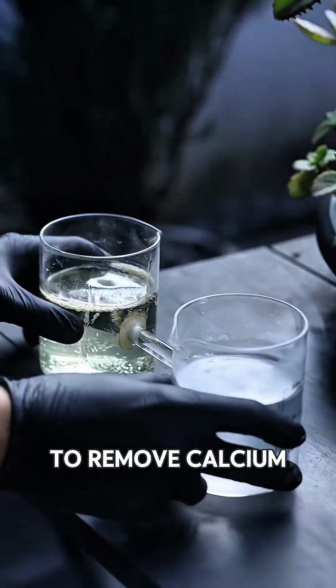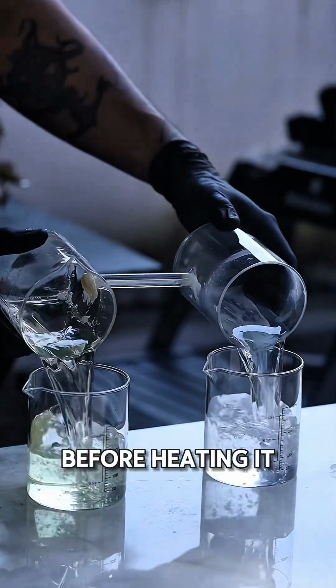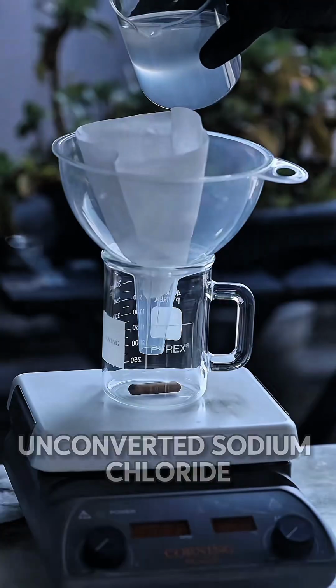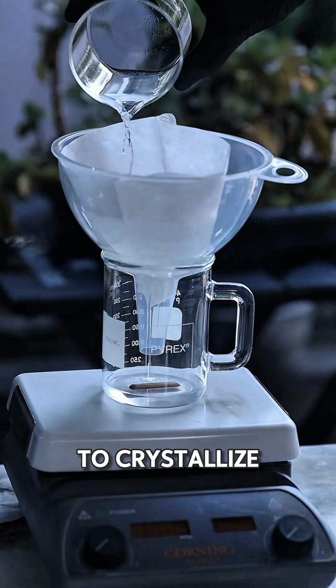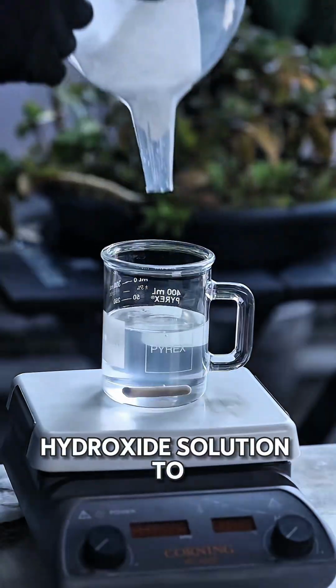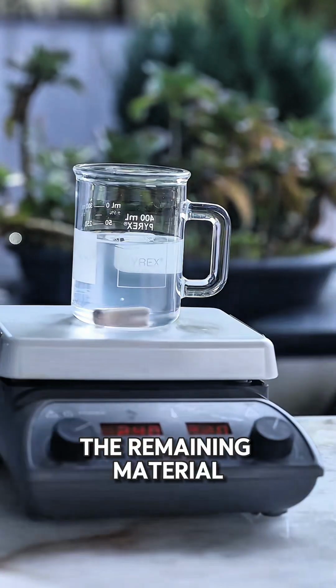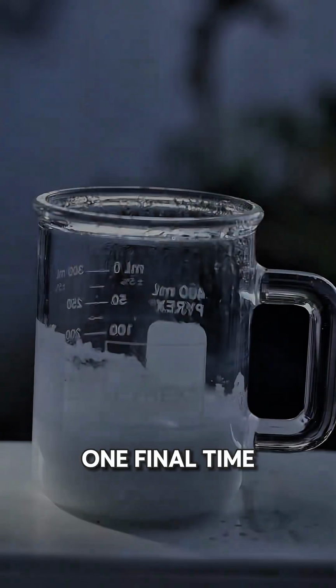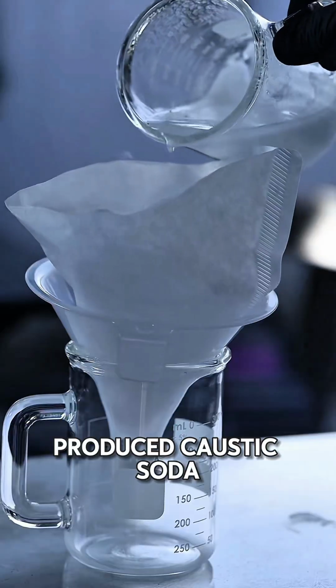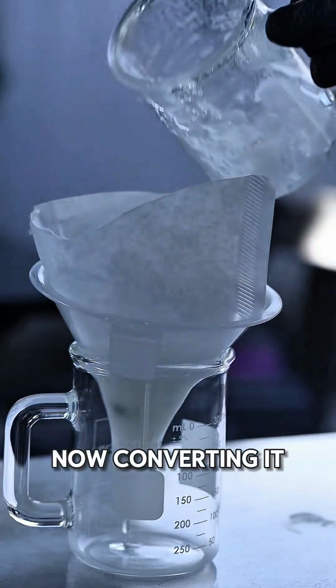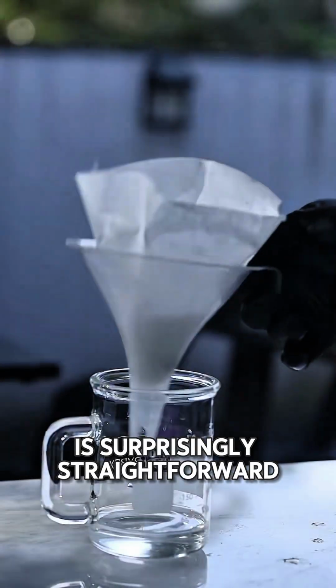I filter it to remove calcium and magnesium impurities before heating it. This causes any unconverted sodium chloride to crystallize, allowing the sodium hydroxide solution to be filtered off. The remaining material is then dried one final time. At last, we've produced caustic soda from salt. Now converting it into metallic sodium is surprisingly straightforward.